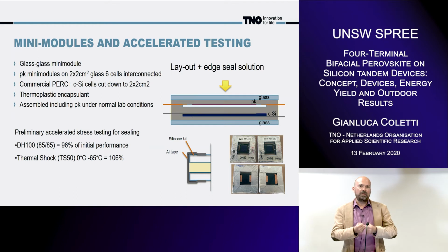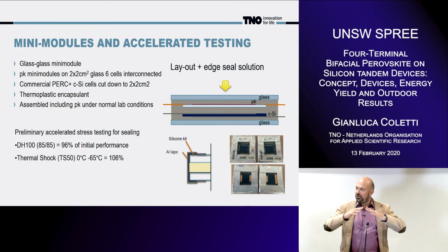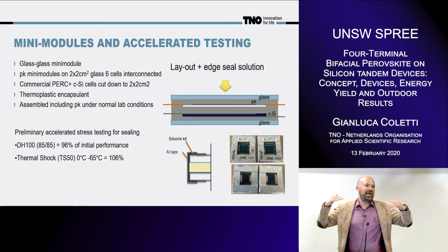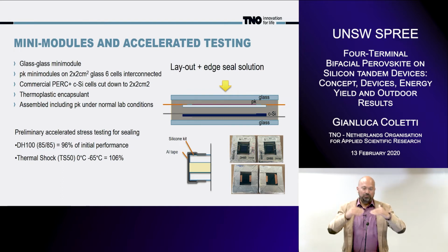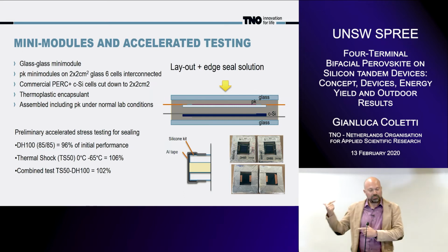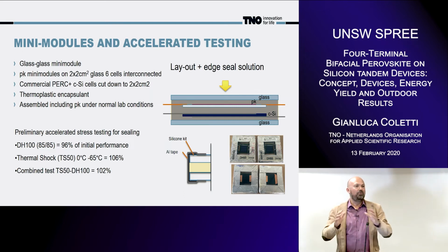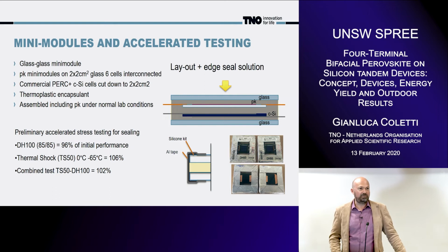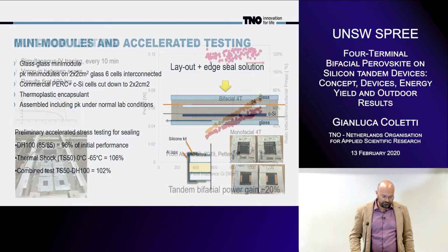Why? Because with the thermal cycle, as I said, you stress the interconnection, but also the edges where the terminals come out from the module. And then the damp heat essentially has moisture trying to penetrate. But the good news is that because of this gain we had before, we actually have the same initial performance. So despite this test not yet being at the IEC level, it's a first indication that, okay, we can put this device on the roof.